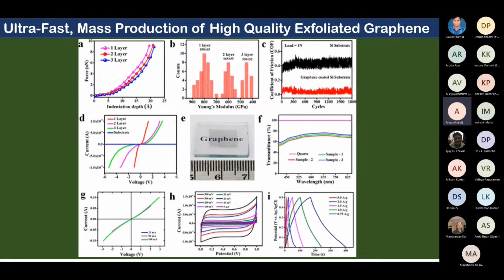Now, once we confirmed the purity, the quality, and the single layer percentage, we thought of showing the complete proof of concept of our graphene. We have done multiple proofs of concept, which you are seeing here. The first one you are seeing here, we tried indenting over the single layer, 2 layer, 3 layer. This was a very sophisticated characterization carried out by the AFM at IIT Kanpur.